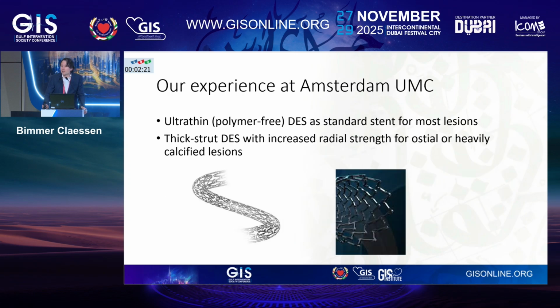And finally, in our experience at Amsterdam UMC, we basically use two types of stents. We have an ultra-thin drug-eluting stent as the standard for most lesions, and we use a thick strut DES with increased radial strength for ostial or heavily calcified lesions.